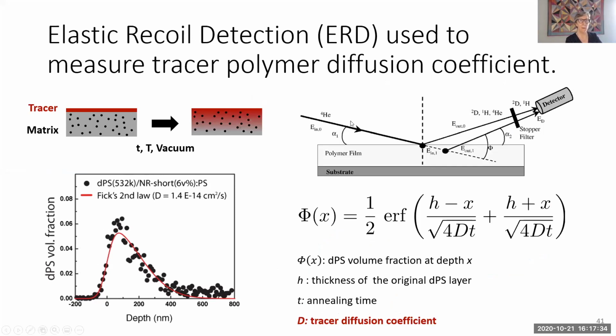We have a helium ion beam that knocks out the deuterated material, and we can use the detector to give us the energy of the deuterium. And so if we have a deuterated tracer, red, and we put a little bit of deuterated material on top of a bulk composite, we can look at the concentration of the deuterated material as it goes into the composite, as a function of time and temperature as it's annealed.